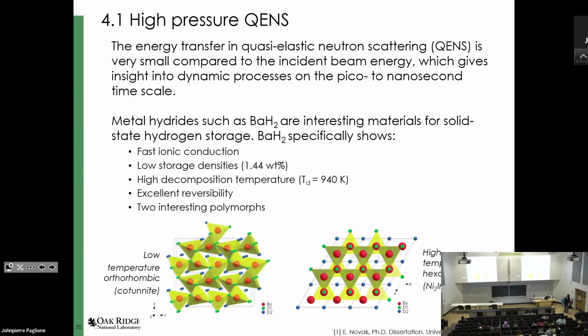Now I know this talk is more about telling you what we can do with high pressure neutron scattering rather than getting into some applications. But I just wanted to briefly introduce this here because it highlights how we were coupling two instruments to do these experiments. The example we were working on was barium hydride. A PhD student, Eric from UTK, was very interested in that, so he was really pushing that project. Barium hydride is an interesting material for hydrogen storage, and it has two polymorphs that you can access with pressure, but also with temperature, that have very interesting behaviors. So the idea was really, can we understand that with QENS? Because QENS looks at a small energy transfer, and so it gives you some insight into these behaviors and hydrogen jumps.